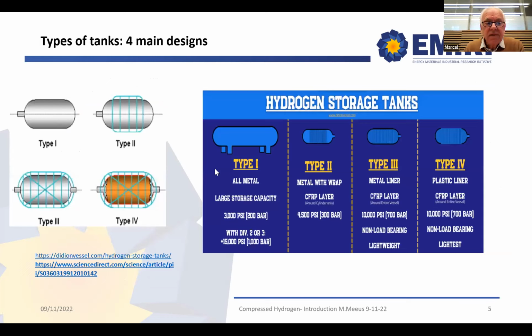We have different tank types, and those are the four main designs. We are talking about type 1, type 2, type 3, and type 4. Type 1 is the all metal version, 200 bar pressure. Type 2 is the metal vessel, but with an outer wrap of carbon fiber reinforced polymer layer, and that goes up to 300 bar. In the type 3 and type 4, we come into the mobility section, focusing on 700 bar, and that can be in the type 3 version, a metal liner combined with the CFRP layer, and type 4 is a plastic liner, with the same outer layer of carbon fiber reinforced polymer.